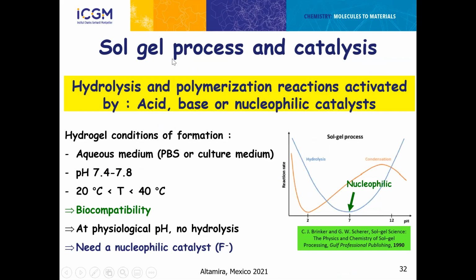Just as I mentioned before, the sol gel process should be activated. If we want to prepare hydrogel for biological application, we have to take PBS, so water PBS at pH 7.4 to 7.8. And you can see here, at this pH, there is no hydrolysis. If you don't have hydrolysis, you don't have polymerization. So for this reason, we have to find another type of catalyst, not acid and not base, but a nucleophilic one. I will explain why nucleophilic is very suitable for this process. And we have to stay in biocompatible conditions.